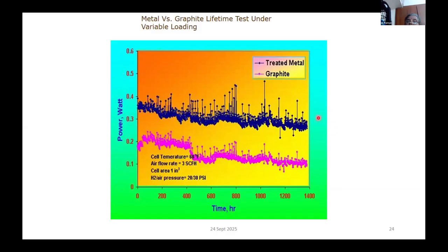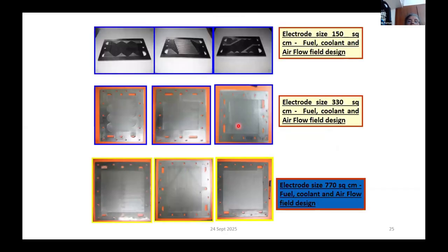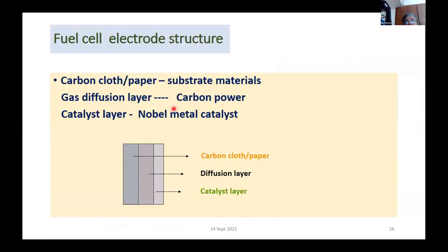So here is an example comparing graphite and treated metal. You can see that the power density when you use a metal-based bipolar plate is very good because of the conductivity and other properties. At ARCI, what we have done is develop exfoliated graphite based plates. These are much thinner. They are made by compression molding, and we can make various sizes. There are many designs, and we have made various types of plates.